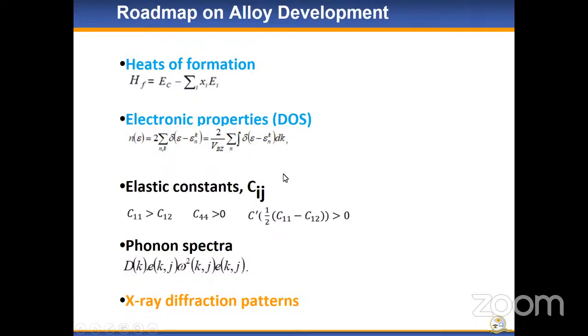We start with the structure and determine its energy, determine the heat of formation, which actually gives us an idea on the stability of the system. And then we also correlate that with some electronic properties in the form of densities of states. So we use this relation just to see how the heat of formation and the density of states are comparable. And from there, we go and look at the elastic constants, then phonon dispersion spectra, and the X-ray diffraction, where in particular we're looking at transformation from various phases.